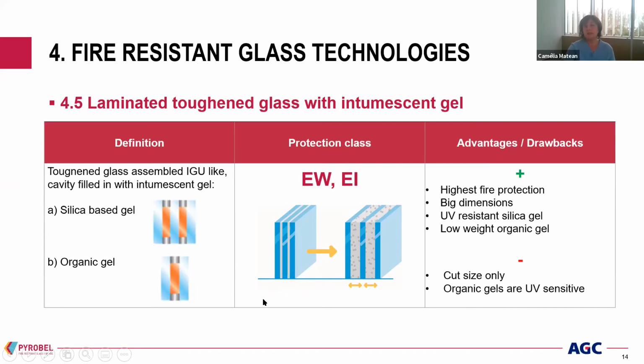The advantage is the highest fire protection. We can produce very big dimensions of glass, up to 5 meters. The inorganic gel is UV resistant, and the organic gel is low weight. The main drawbacks are that it is only available in cut size, and this will lead to longer delivery time. And organic gels are quite sensitive to UV. They become yellowish during aging.